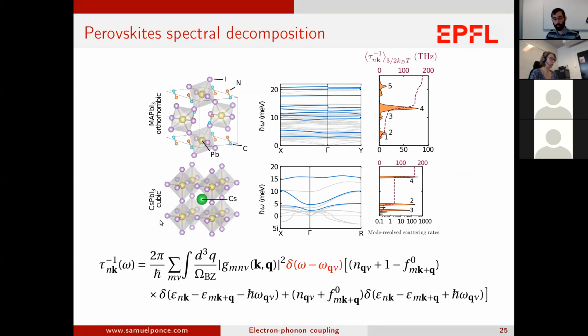But this is a good point. In the case of cesium lead iodide, we have soft phonons, and so we simply neglect them. We've tested that, because in general this is not something you should do. But cesium lead iodide is a material that, because of symmetry, has no acoustic coupling. You can see, this is a log scale, you have no contribution from those modes. So even if those modes were positive, they would not contribute. And so in that case, we believe it's a relatively good approximation to neglect the soft modes. So indeed, those are completely neglected, yes, for the electron.